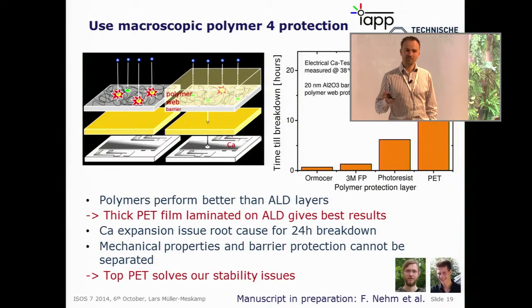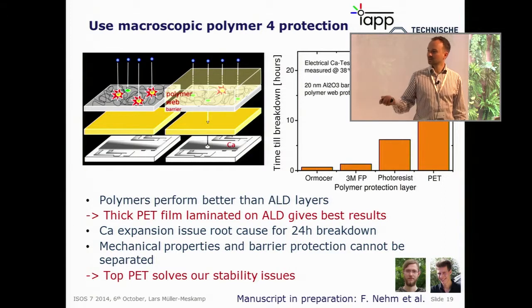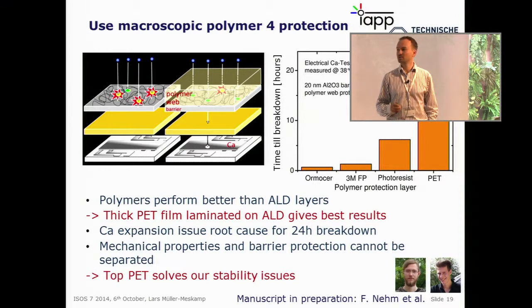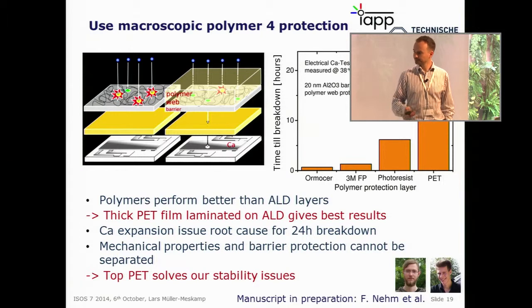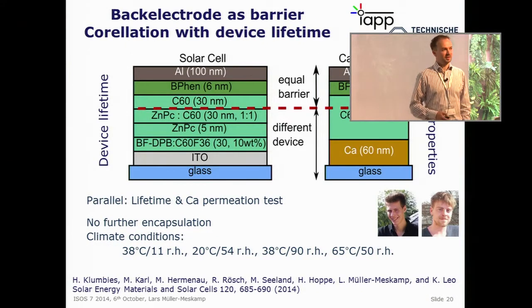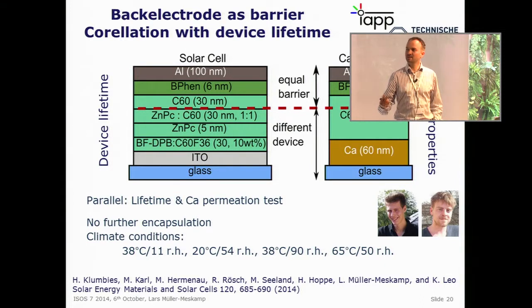So especially for the thin ALD layers, they might perform a bit better, but still it's clear that you need some kind of protection on your thin film encapsulation. Otherwise, it will not stand ambient atmosphere. Another nice thing which we can do with our calcium test is actually put it into a device or replace the device with the calcium test, basically what I've shown in the beginning.